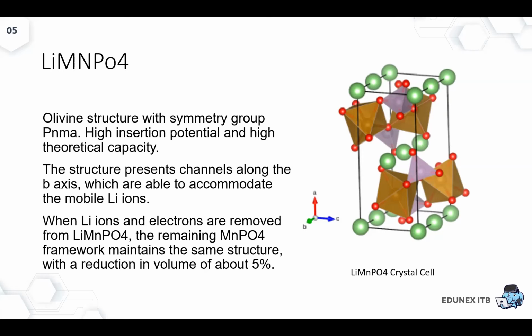Lithium manganese phosphate has an olivine structure with symmetry group PNMA, which also has a space group number of 62, and it has high insertion potential and high theoretical capacity, which is why I chose this compound instead of its currently more popular alternative, lithium iron phosphate. The structure that you see presents channels along the b-axis, which is where it transports the lithium ions. When lithium ions and electrons are removed from lithium manganese phosphate, the remaining manganese phosphate framework maintains the same structure with a reduction of volume of about 5%.